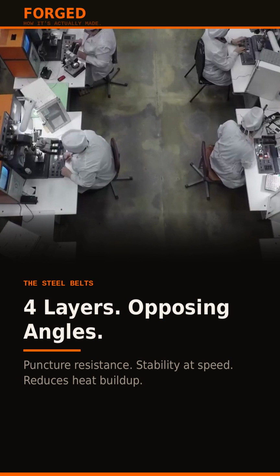The steel belt package is the most critical structural element. 4 layers of fine steel cords, each cord made of multiple individual wires twisted together, are embedded in rubber and placed around the circumference of the tire, running at opposing angles to each other. These belts are what give a radial tire its stability at speed and its resistance to punctures. The cords run almost horizontally, stiffening the tread area and reducing the footprint deformation that causes heat buildup. On top of the belts goes a cap ply, a final layer of nylon that holds everything together at high speed. Then the tread rubber is applied.